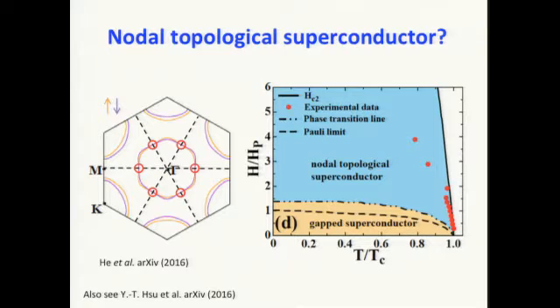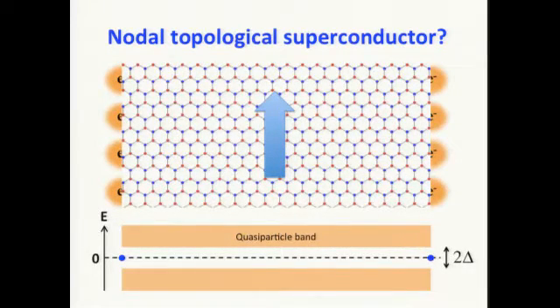So it turns into a nodal superconductor, and this is a rough picture I came up with: if you apply a magnetic field higher than the HP, the bulk of the material is largely gapped except for several nodal points with some zero energy Majorana modes on the surface of the material. So it's quite an interesting system to see whether this is the case in the future. Okay, with this I thank you for your attention.